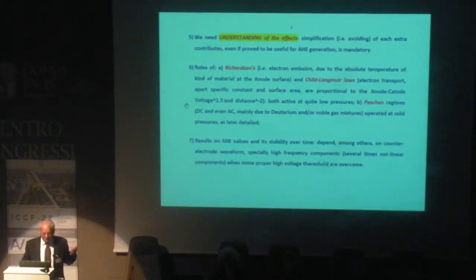During the MID conference, 6 months before, we explored the effect of electrons. So it means the Richardson law, well known to people, and the Child-Langmuir law about the movement of electrons. Later, we realized it was not enough, so we explored the Paschen regime that Paschen developed about 130 years before, in Germany, to study insulation properties, high voltage insulation. So the experiment was made at room temperature and DC condition. This experiment gives us a lot of quite important information, how to manage the system to avoid that the excess heat vanishes over time.